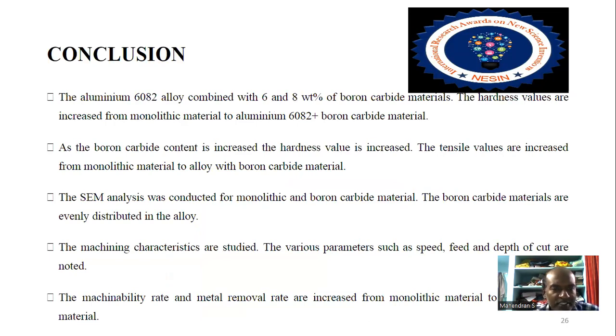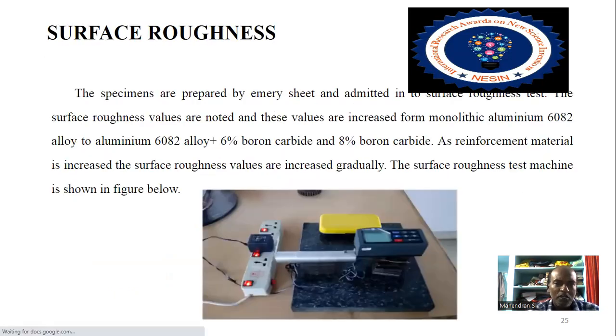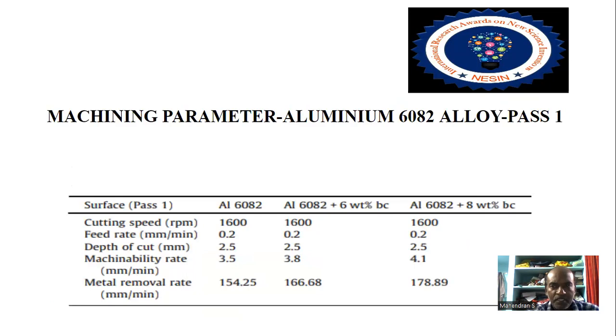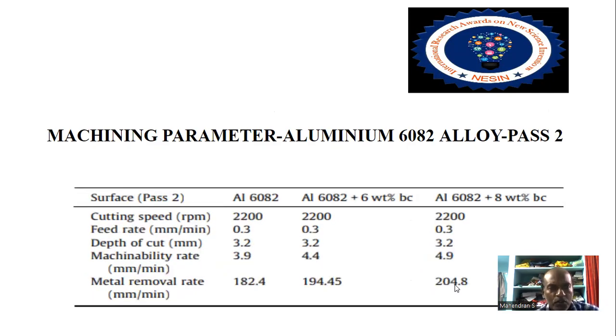Next one, the machining characteristics are studied. The various parameters such as speed, feed, and depth of cut are noted. The machinability rate and metal removal rate are increased from monolithic material to composite material. These are the set one. Machinability rate is also increased from aluminum 6082 to aluminum 6082 plus 8% of boron carbide, 3.5 to 4.1 millimeter per minute. Metal removal rate also increased 154.25 millimeter per minute to 178.89 millimeter per minute.